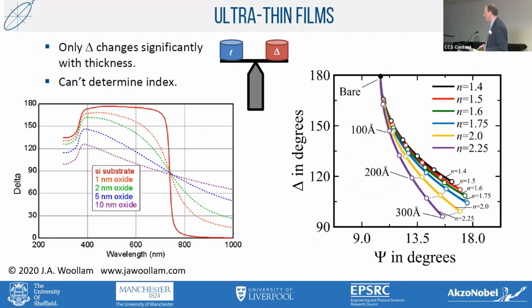So in very thin films, ellipsometry essentially is a very sensitive way of measuring path difference for S and P polarized light going through a sample. So it depends on the optical path length, it depends on the thickness that you're going through, and it also depends on the refractive index. And you can convince yourself that in very thin films, it's really only sensitive to some product, some first moment of the refractive index over the path, and that makes it slightly problematic in extracting it when we get to these very thin films.